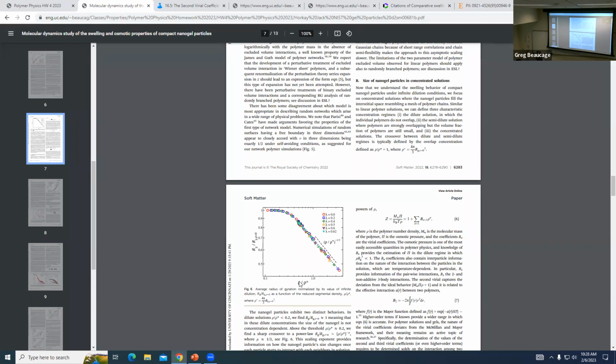This rho star, the way you calculate, it wouldn't give you where it, oh, I know why. Rho star is calculated with RG, so it's just like the mass divided by RG cubed. And RG, we know, is like 2.45. RG is R, the end-to-end distance for the linear chain. So the actual size of that blob is like 3 times bigger, and 3 cubed is 9. So if you divide 1 by 9, you get this number, like 0.1 or something, a little bit higher. Right, so it does kind of match up. It's just RG wasn't the right number to use for phi star. Should have used an actual R.